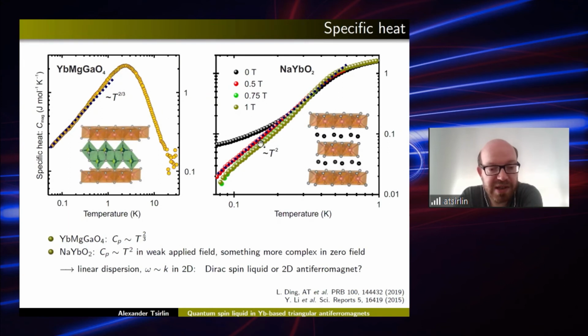Now let's see how it affects the low energy excitations. Again, the first probe is the specific heat. In the previous compound, we had this unusual sublinear behavior, which was initially interpreted as spin excitations. In NaYbO2, it actually looks rather different. If we measure it in zero field, then there is no power law behavior at all. You see that this black curve doesn't show any straight line in the double log coordinates. But if we apply a small magnetic field, then we get to a very clear T-squared behavior, which, well, can have different interpretations.